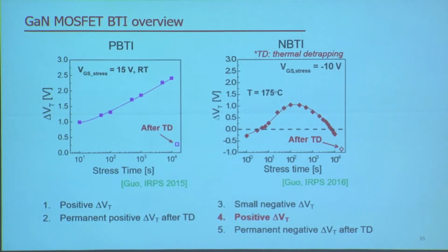Okay, so I have talked about regimes 1 to 3, and now I will talk about regime 4, which is also on the negative bias side, but it's recoverable. What's very interesting about regime 4 is that you see this positive VT shift, which is really a unique phenomenon of the gallium nitride system that hasn't been observed in silicon or silicon carbide. So that's very interesting for us to study.